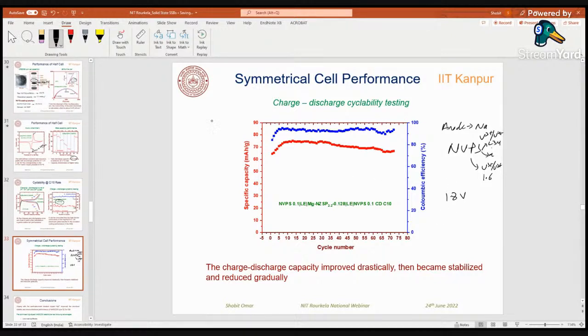We tested this solid state battery, and initially the performance was not very good, around 65, but then it activated, and you get a stable performance till 71 cycles. The performance increased from 65 to around 75 milliampere hour per gram, and the Coulombic efficiency is above 90% in most of the cycles.